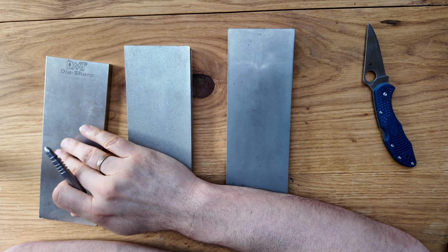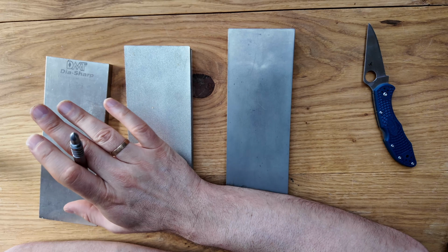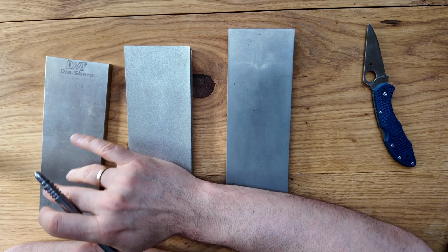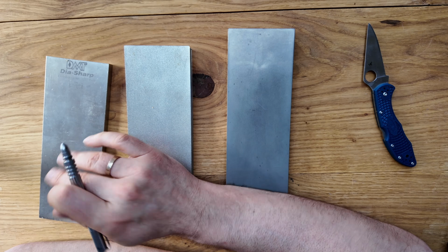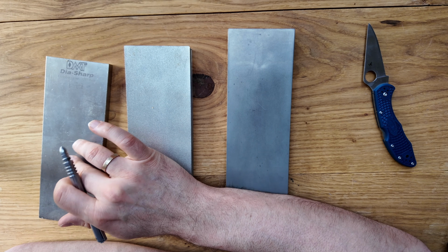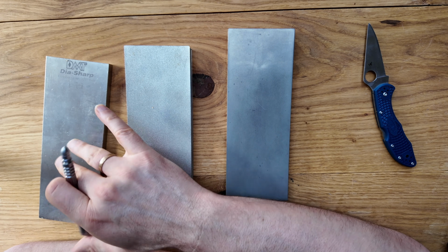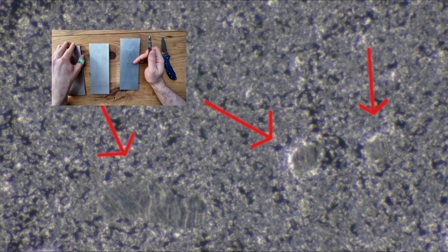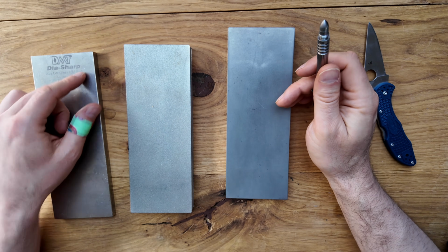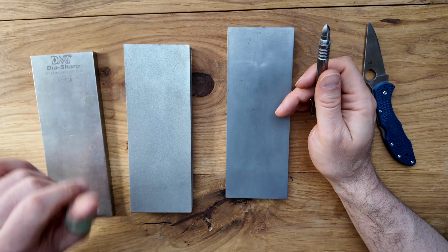So at this grit level, consistency matters more than everything else, because a few oversized grains would leave scratches that do not belong there. This stone looks like a properly graded, well-manufactured plate. There are a couple of smooth, reflective spots visible on the surface. These do not look like diamond grains. They lack the angular, faceted texture of the surrounding abrasive, and most likely these are areas where a diamond has been pulled out during use. Whether they affect edge performance is something the microscope footage of the edge will answer.